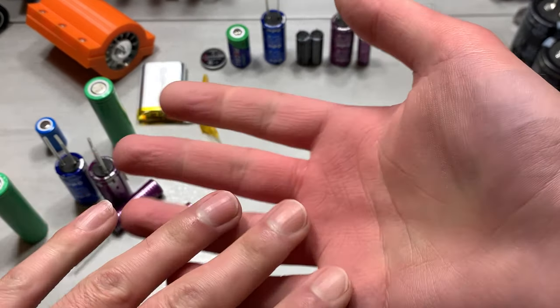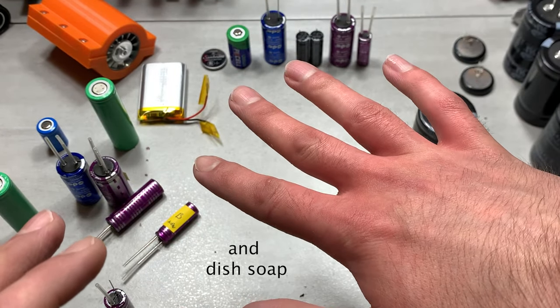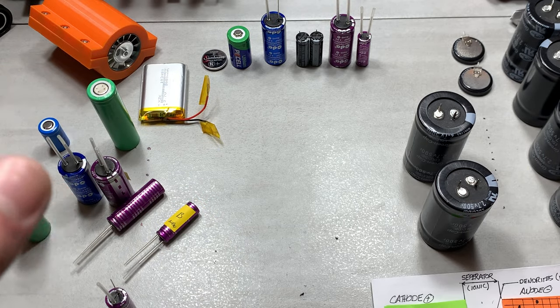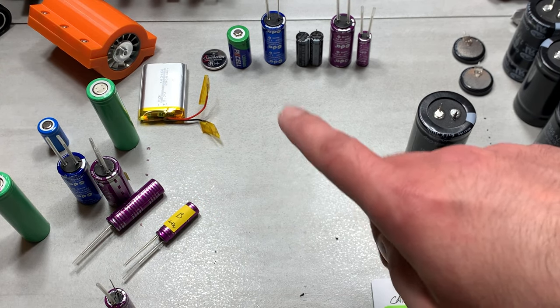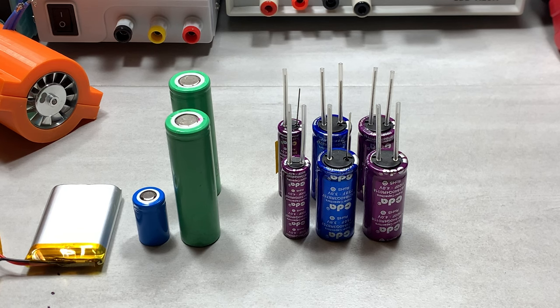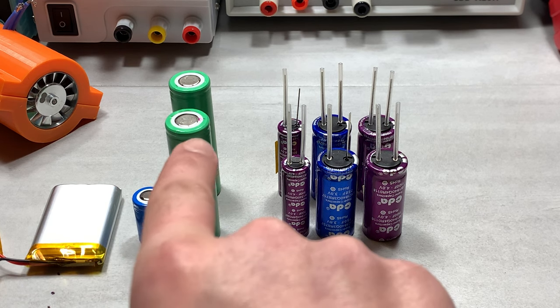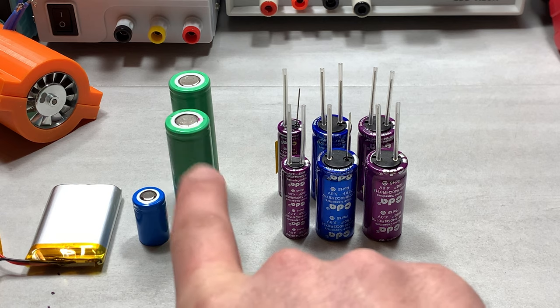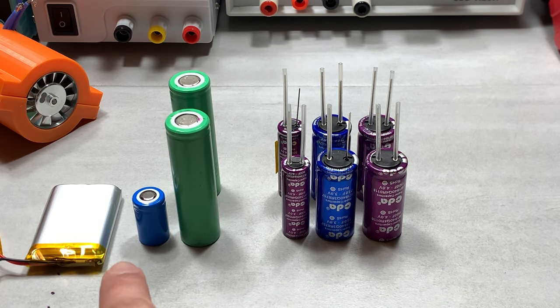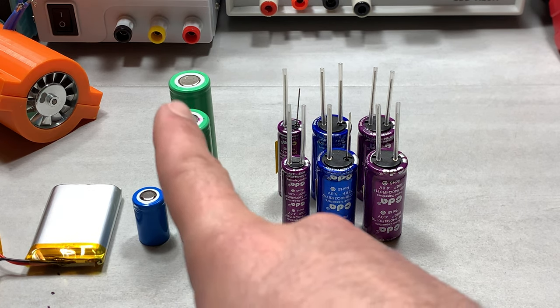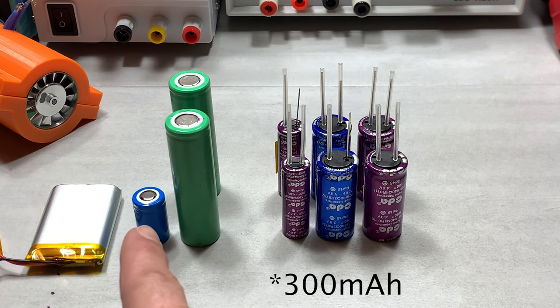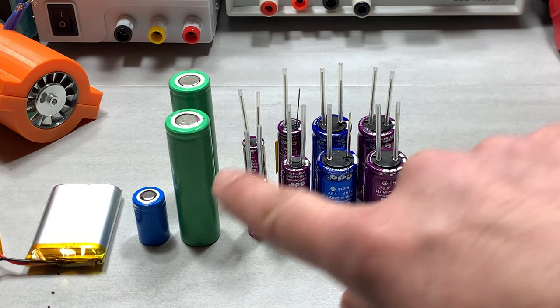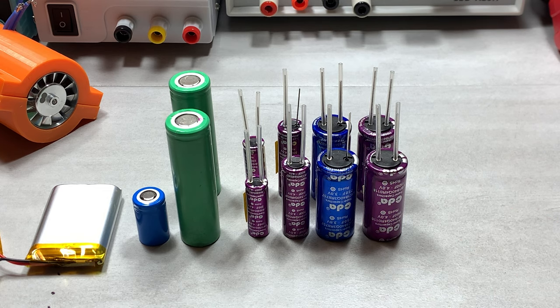So after having washed my hands like 5 times in a row with hot water and scrubbing very, very thoroughly, we can now get into charge rate. So here I have 3 different types of lithium ion cells. The first one being a lithium polymer battery cell. The second 2 being the standard lithium ion 18650 and the baby version of that, the 14250. With these ones being 2.2 amp hours, and this one being 300 milliamp hours. And then finally, I have 4 of the highest energy density lithium hybrid supercapacitors I could find.